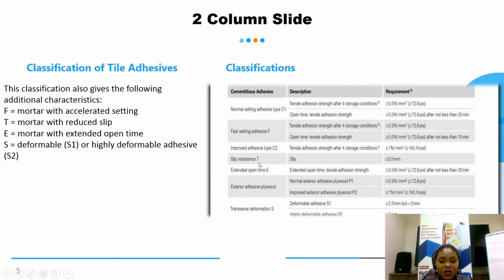Then slip resistance T, very important. It's really important to have a non-slip adhesive. So make sure you look for the T classification on the tile adhesive you're purchasing or using for tiling your high-rise building, and the requirement is less than or equal to 0.5 millimeter. Extended open time, you have greater than or equal to 0.5 Newton per millimeter square after not less than 30 minutes.